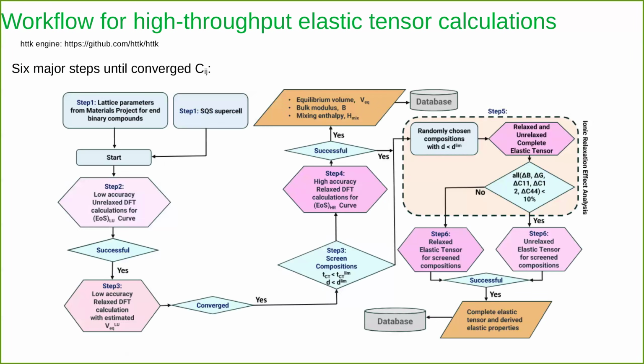So to get the elastic constants for such alloys, and particularly in a group of materials where you can have dynamically unstable phases, I translate that to calculations where the material doesn't exist, or the calculation, whatever DFT engine you are using, will not converge. You need a very sophisticated high-throughput workflow, and that's presented here, where we have 6 major steps to filter out all the candidates where we don't want to do calculations because it will take so much time.